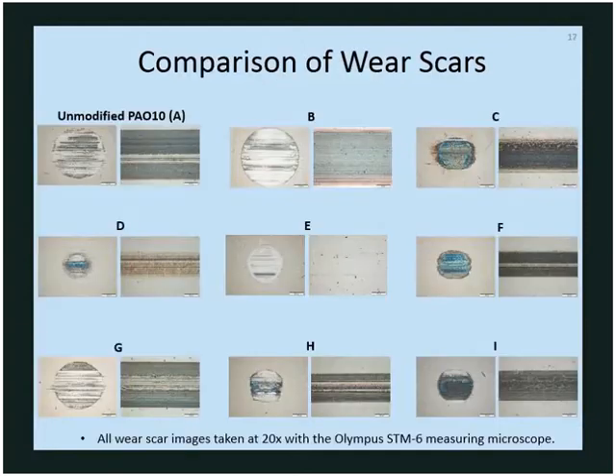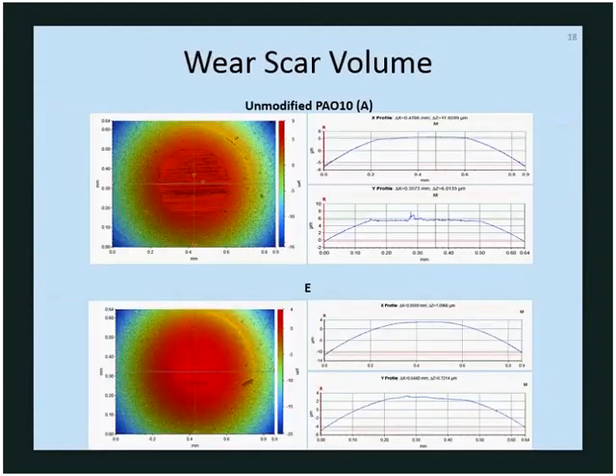And then wear scar images were taken using a measuring microscope at 20x magnification. The larger the wear scar, the worse the anti-wear property is. So the unmodified oil has a lot of discoloration and a large wear scar. However, the oil that exhibited the low friction coefficient is sample E. You can rarely see a wear scar on the flat at all, and a very small wear scar on the ball. So it also has good anti-wear properties as well as low friction.